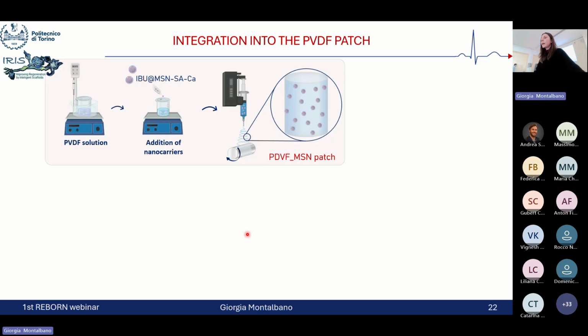The developed nanocarriers were then incorporated in our polymeric patch by following the previously optimized protocol. The carriers were directly incorporated in the polymeric formulation and then processed by the optimized electrospinning process.